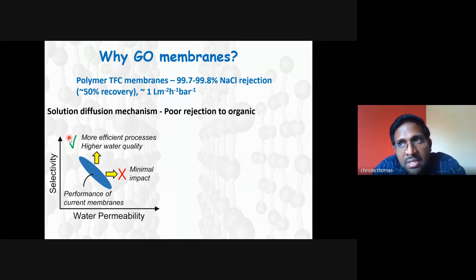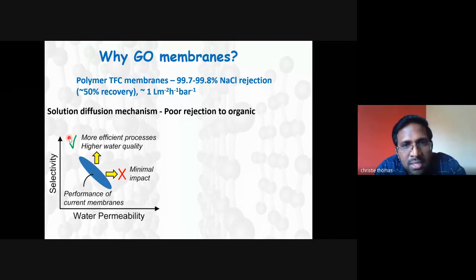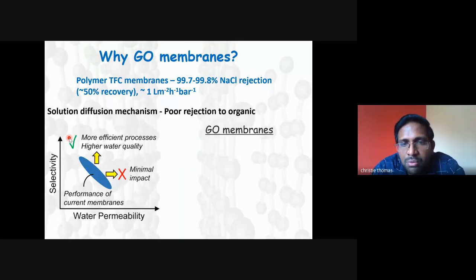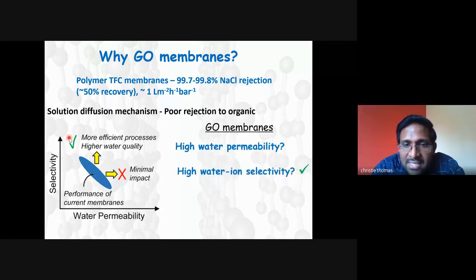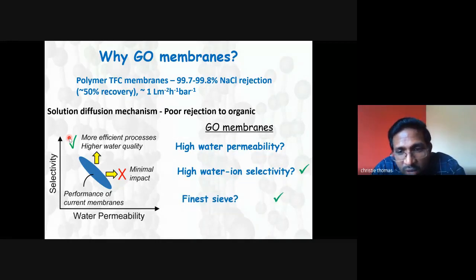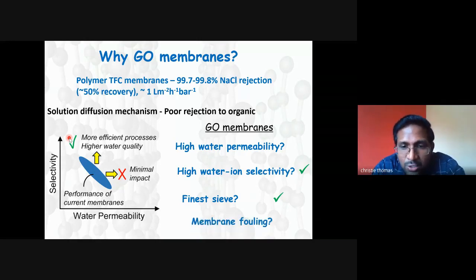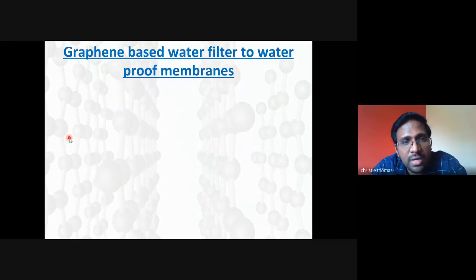Actually, high water permeability has minimal impact because the polymer TFC membranes already have good water permeability, but the selectivity is very low. There comes the importance of GO. GO has high water ion selectivity. It has the finest sieve, so it can reduce the post-treatment and pre-treatment steps in an industrial plant. Okay, and also it can reduce membrane fouling, but that is under investigation only. So that's the prospect of graphene oxide membrane.